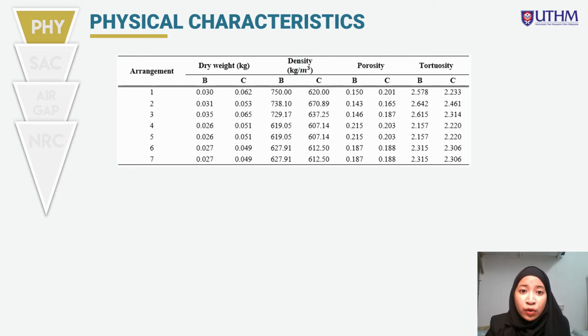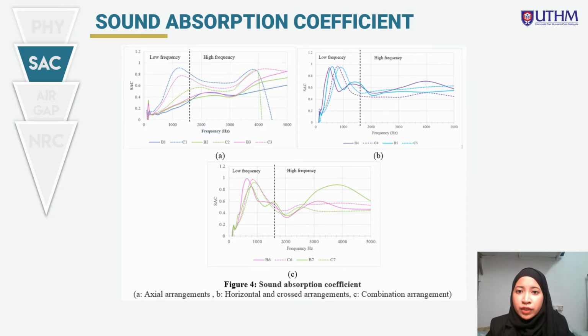The samples with horizontal and cross arrangement share the same value of dry weight, density, porosity, and tortuosity due to the same layers of stalks being used to fabricate the samples. The same goes for the combination arrangement. In figure 4a, we can see clearly that samples fabricated with a smaller diameter range demonstrate good acoustic absorption compared to samples with a bigger diameter range. Unfortunately, samples C2 and C3 suffered a severe decline from an SAC value of 0.8 to 0 absorption.